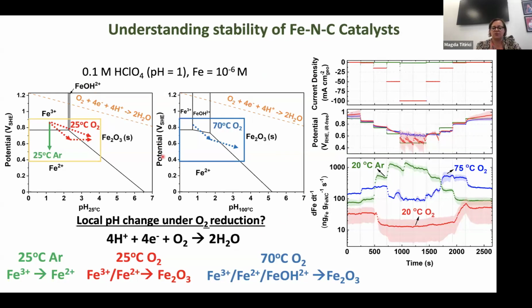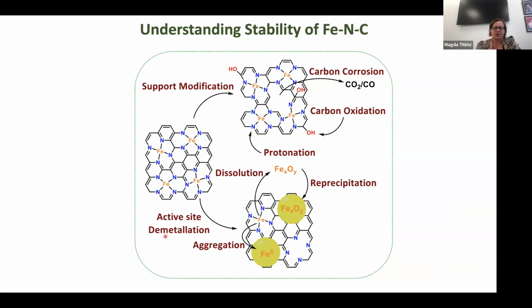But most of all, you would also have local changes in the pH because you're changing the concentration. So you will have massive changes in the pH. You would see it go from acidic to almost alkaline once this reaction happens, because you have a constant change in your proton concentration, which will also affect the dissolution of iron. So it's very complicated with the single atom catalyst. As I said, they degrade quite a lot. They form iron oxide, they precipitate in the solution, they reform, the carbon gets protonated, the carbon gets oxidized, and so on.